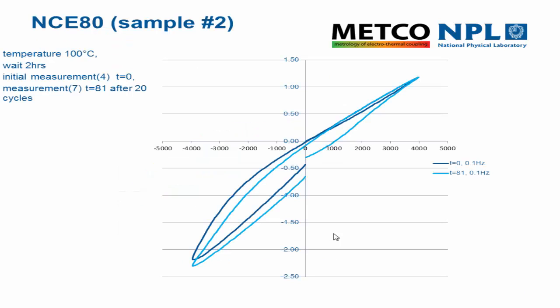Torsten did some excellent detective work on this to try and understand what was going on. The reason is that the PTB measurement, we've seen the very large interferometer system, takes a long time for temperature stabilization. The actual measurement process is not a high frequency measurement. It uses very, very slow electrical cycles, and those time factors had a significant influence on the measured results.